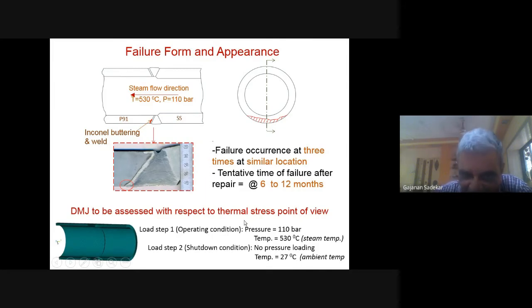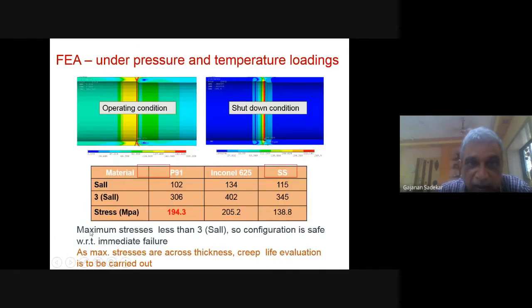First, we did an FEM analysis of it. We considered the operating condition and the shutdown condition. In the operating condition, pressure is 110 bar and temperature 530 degrees; in the shutdown condition, no pressure loading and the temperature was 27 degrees. We analyzed these cases, and then we found the material stresses in the weld joint: P91, that is the alloy steel, Inconel, and the SS. Inconel is that small buttering I told you about. So we found the stress levels.